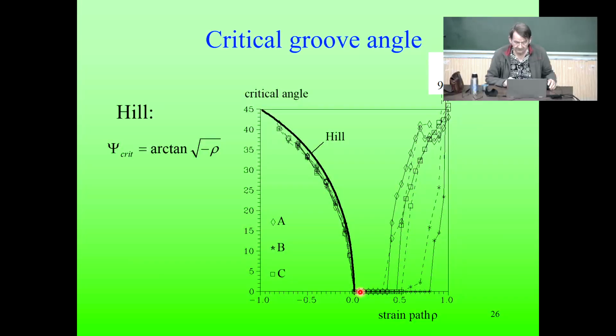Well, the polycrystal simulations confirmed very well the Hill prediction. So his theory is good for the negative part. And concerning the positive part, which is starting here, where it is 0, yes, but not everywhere. In a certain strain path, approaching the equibiaxial, there is strong texture dependence for the groove angle. So the polycrystal simulations confirmed Hill's theory for the negative part and did not confirm his theory for the positive part.